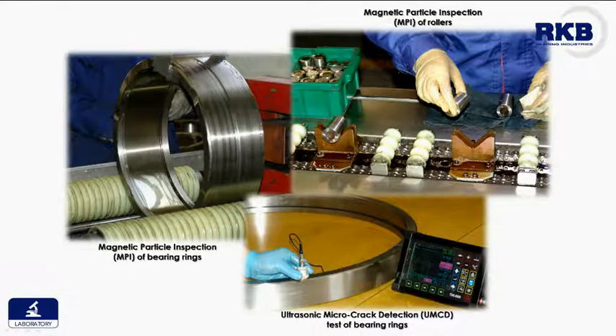Specific non-destructive controls, like the magnetic particle inspection for detecting superficial microcracks, and the ultrasonic microcrack detection for undersurface microcracks location, are regularly performed on rings and rollers during the production process. Moreover, a visual check of the parts ready for assembly is constantly carried out to avoid any noticeable anomaly. Selection of rolling elements and rings in groups of defined grade for correct matching is made by the RKB assembling department in order to obtain the radial internal clearance specified by the pertinent bearing technical drawing.